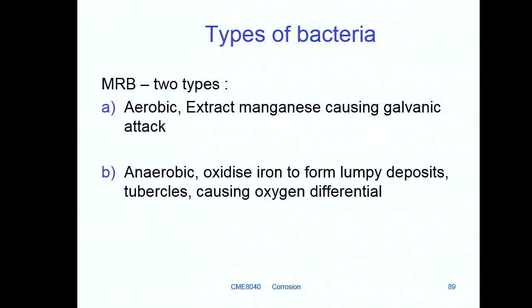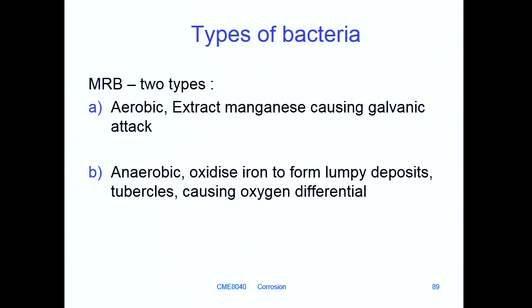And the bacteria tend to live in little habitats, quite often as what they call tubercles, little lumpy sort of dome-shaped structures on the surface, under which you've got some pitting occurring. So before you get a continuous film, you get these lumpy tubercles.